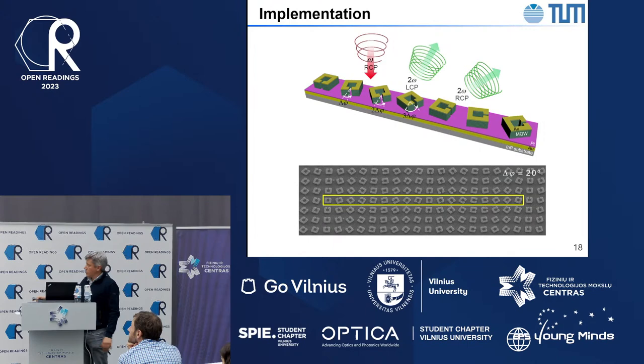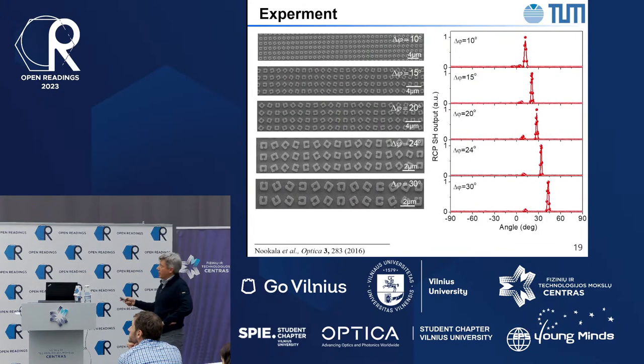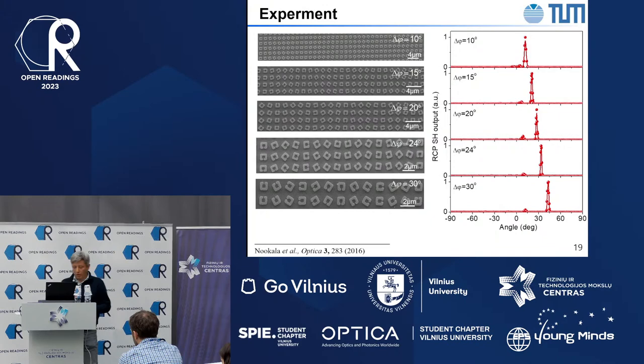And indeed, of course, as expected, we could see that our second harmonic beam for the right circularly polarized input and right circularly polarized output is tuned in a particular angle according to the phase gradient that is introduced in the metasurface. This is just the simplest demonstration of how phase gradient can be used to control the beam. You could also, of course, think of other configurations where you, for example, add orbital angular momentum, produce Bessel beams, and all the other exotic beams by controlling the local phases of the nonlinear response. You could also use voltage tuning to achieve the same effect.